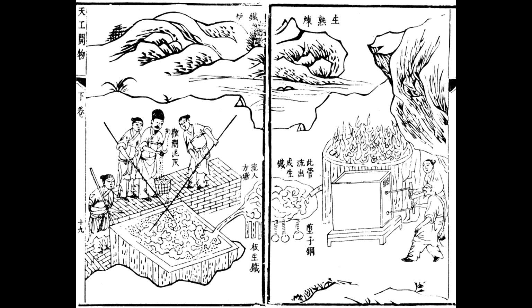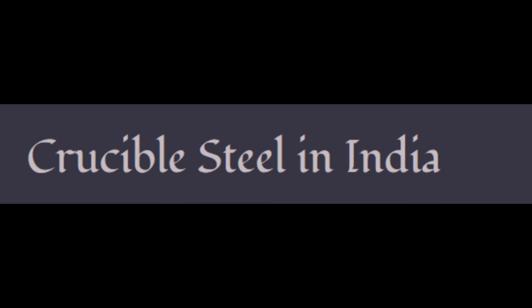Even as silk, Buddhism, tea, gunpowder, and all sorts of other things quite cheerfully crossed those same cultural and geographic boundaries. This becomes, I think, clearer when we compare this to the contemporary method of producing steel in India, which, while perhaps not as efficient as Chinese cast iron, did produce a pretty clearly superior product. Crucible steel in India. While Chinese cast iron products do not seem to have been distributed widely over trade networks, beginning at least as early as the Roman period, Indian steel, which the Romans misunderstood as being from China since it arrived on the same trade routes as their silk, was.